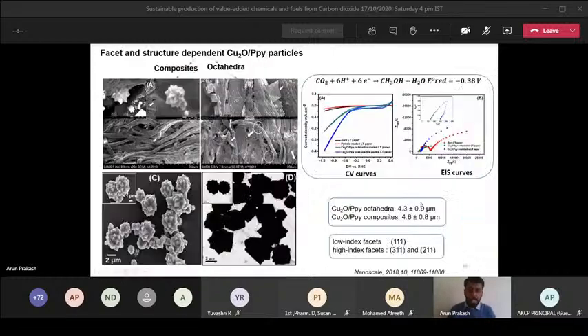This is the morphology of the particles which we prepared in this work. We can prepare a flower-like structure. As I told, instead of having a bulk material, if you go for nanomaterial or micro-sized material, and this is a micro-sized material, a microparticle, but it has different facets, and this helps to achieve higher selectivity. We can prepare either a flower with one single octahedra like here, or with multiple octahedra. This is the morphology, and you can observe the activity.